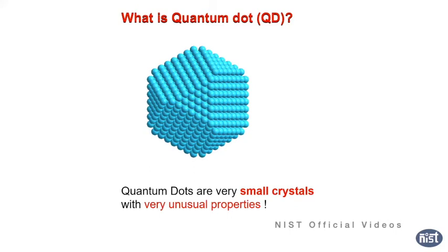And when it goes to quantum dots, the quantum regime, quantum means it should be confined along the band gap. That means the diameter or length or radius, whatever you see, sometimes quantum rods or quantum platelets, should be below the effective radius. For cadmium selenide, it should be below 6 or 7 nanometers. Generally 1 to 10 nanometers is perfect for quantum dots.